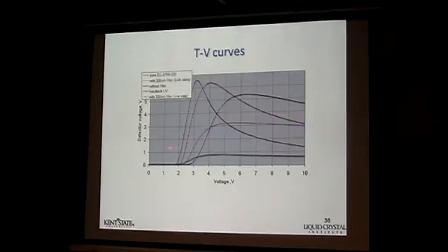Before you open up the cell, you want to study the electro-optical properties. So you take it to the setup and measure the light transmission as a function of applied voltage. For VA mode, the molecules start with vertical alignment. You apply the field, and they start to rotate, with the dipole aligning in the direction of the field. So you get an increase of light transmission as a function of voltage increase. And then there are different ratios because of the type of liquid crystal that you use.